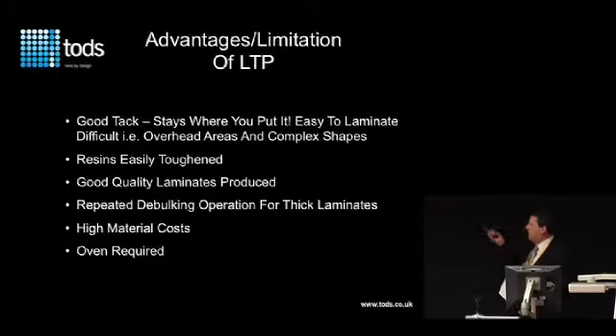When you consider particularly sonar domes, one of the major issues that we have is actually holding the materials in place prior to applying a vacuum bag. So low temperature prepreg scores very well. It's got tack, it will stay literally where you put it. The resins are relatively easily toughened. Most low viscosity vacuum infusible resins aren't toughened because the toughening agents increase the viscosity, and it makes it difficult for you to actually infuse. Our experience was the quality of laminates was very good.